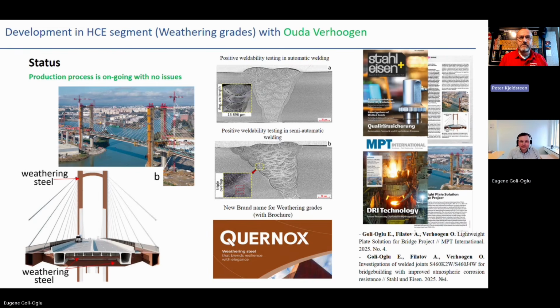What is the chromium content? 0.40, 0.50. Okay. So not so high. And then, in addition to protect steel and to make it stronger from one side, and then to avoid surface defects from the other side, we are also adding a combination of niobium, vanadium, and titanium as microalloy to this material. It's everything from the periodic table, a little bit from the top side.